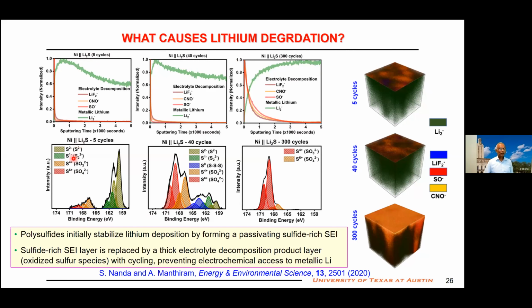Obviously, polysulfide has diffused, crossed over from the cathode to the anode, so it forms some sulfide species. That's okay. But what we also see is these sulfur oxygen containing species, oxidized. A lithium sulfur battery needs a little bit of lithium nitrate. So lithium nitrate along with the salt causes an oxidation of the sulfide species to these oxygen containing species, and that keeps, you see here, oxygen containing species increasing.